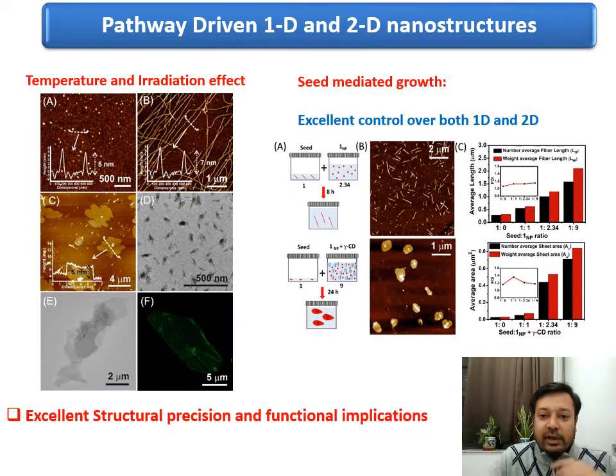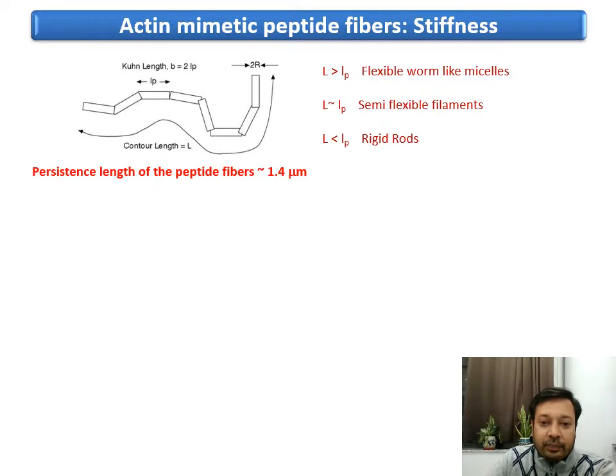So we thought, can we really control the shape and the size of such nanosheets? And as you can see, we have followed it. We can form very nice nanofiber, nanoparticle, and then nanosheets like this, you can see. And using a suitable seed and monomer, we can have very nice control over the shape and size of such material, which is in a way very new.